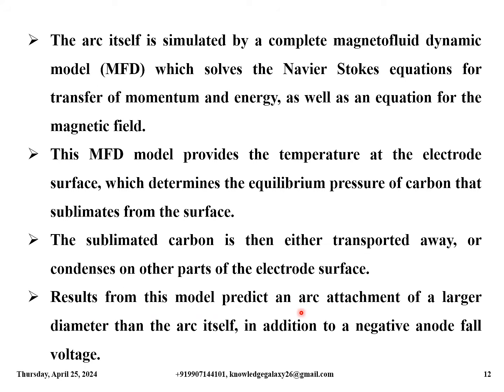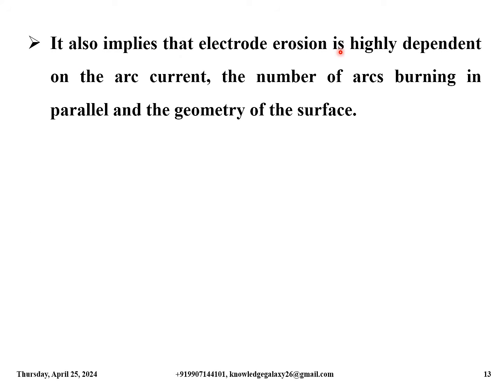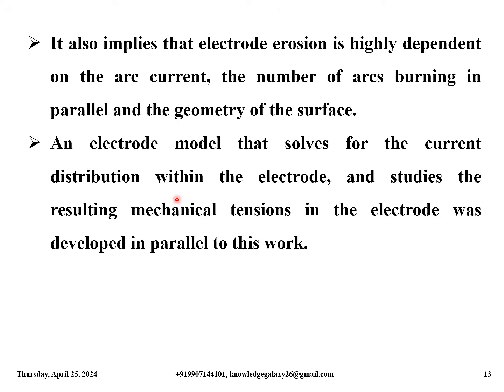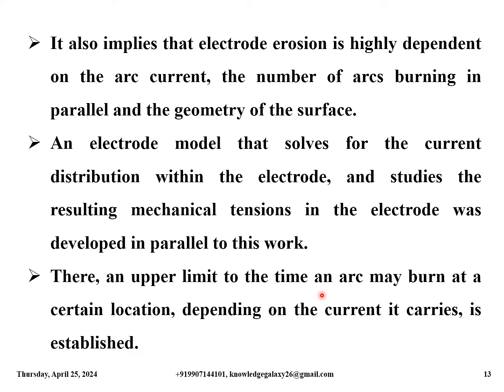Results from this model predict an arc attachment of a larger diameter than the arc itself, in addition to a negative anode fall voltage. It also implies that electrode erosion is highly dependent on the arc current, the number of arcs burning in parallel, and the geometry of the surface. An electrode model that solves for the current distribution within the electrode and studies the resulting mechanical tensions in the electrode was developed in parallel to this work. There, an upper limit to the time an arc may burn at a certain location, depending on the current it carries, is established.